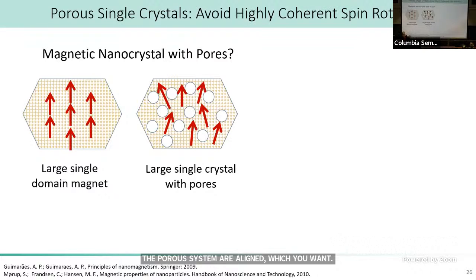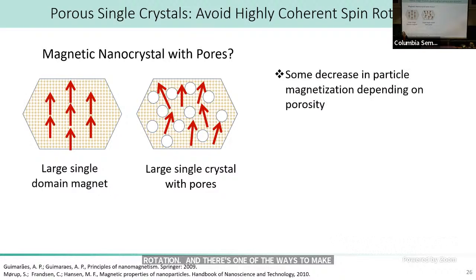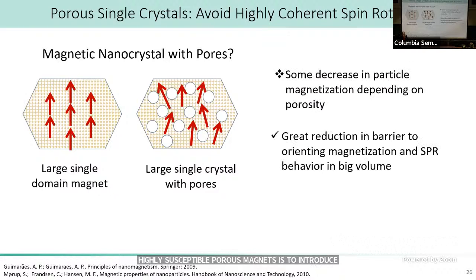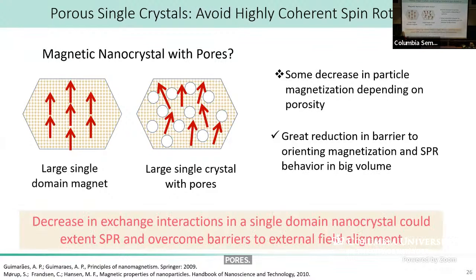And that's one of the ways to make highly susceptible porous bulk magnets, is to actually introduce pores. So our question is, could we do this on the nanoscale? And the hypothesis was that we could decrease some of the interactions that were causing these barriers to rotation by producing a system that's highly crystalline. We can't give that up because that has to do with the ultimate magnetization. But could we put enough defects or pores into the system to allow the spin rotations to occur more easily?